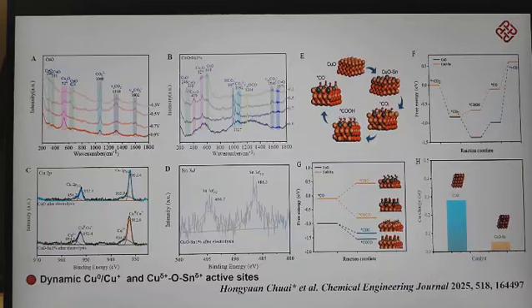When tin atoms are introduced into copper oxide, the free energy barrier of CHO increases significantly, suppressing ethylene production. Thus, the above results demonstrate that product selectivity can be tuned by introducing tin atoms.